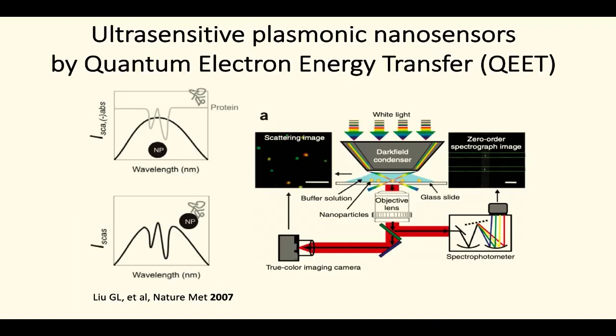And what Luke Lee discovered was that if there is a protein or a molecule on top of a gold nanoparticle, and that molecule absorbs light, has a UV spectrum, in the same wavelength that the gold nanoparticle scatters light, there is an energy transfer between the particle and the molecule. Because when they looked at the spectra of those nanoparticles with the protein on top, they saw the UV-Vis spectra of the protein inside the spectra of the nanoparticle.